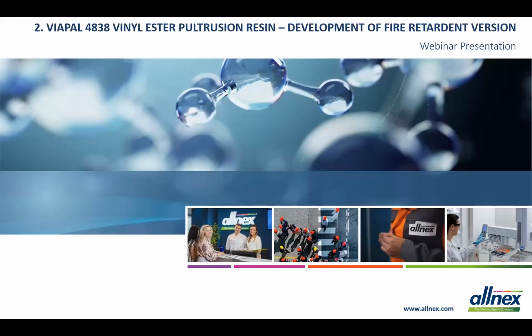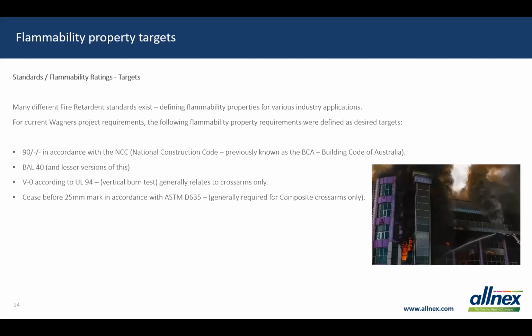Now, in terms of the work we're doing to develop a fire retardant version for this particular project, a fire retardant version of the resin we currently supply Wagner's, which is a fairly high performance vinyl ester called Viapal 4838. It's an epoxy bisphenol A based vinyl ester resin, has very high heat distortion temperature, good line processing properties, and we're looking to see if we can modify that to provide these properties here.